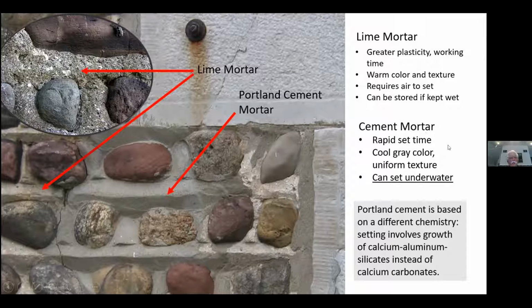And these mortars tend to be much more rigid, but they set more rapidly. They have this kind of very cool gray color and uniform texture. And they don't have the elasticity that lime mortars do. So when they're combined with lime mortars, they oftentimes don't play well with them. And so you can see some cracking, which is going on here right at this joint through here.